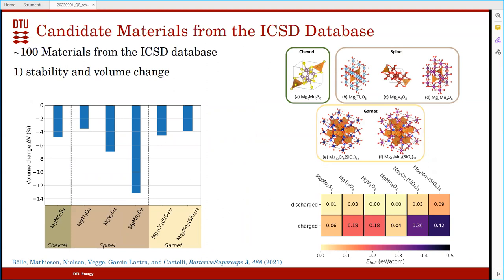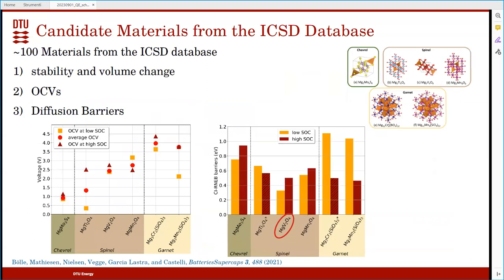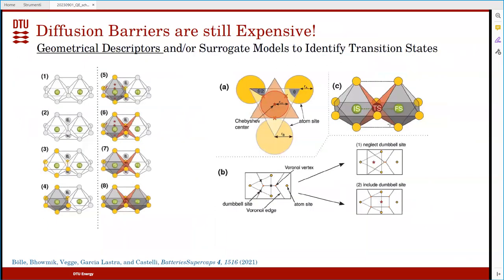We do this, so we have just a few results. We take about 100 materials from the ICSD. We calculate stability and voltage. We calculate OCV and diffusion barrier. And then we end up with this magnesium vanadate that is one of the possible good materials that one of our collaborators in Spain is trying to synthesize. But again, we have also used this for calcium ion batteries, and the method is very easy.